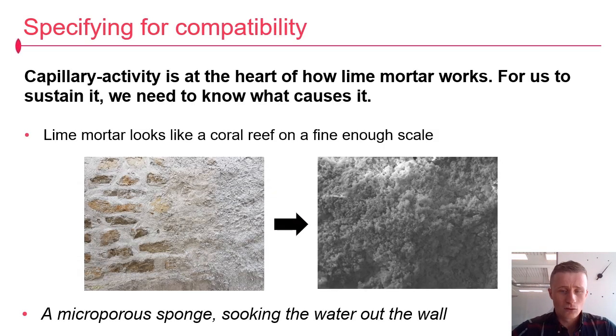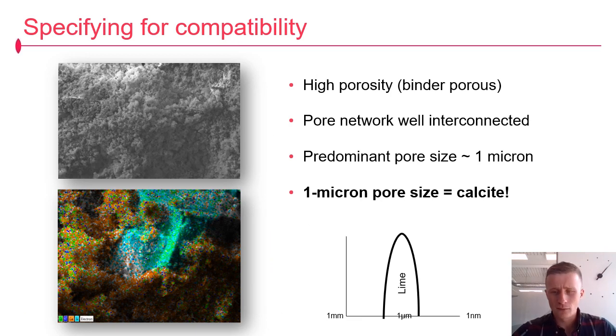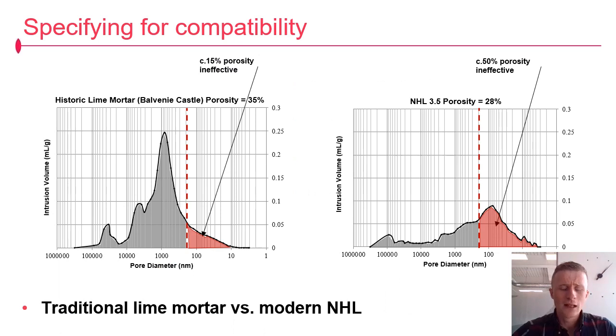So when you look at lime mortar on a fine enough scale, it is essentially a sponge, a coral reef looking thing through a powerful enough microscope. That's a sponge soaking up that water and drawing it out of the wall, and with the moving water come the soluble salts. What creates that sponge? Well, when you look at it through an EDX microscope and identify the minerals at work here, what you're looking at is calcite, that's carbonated free lime, in the mortar mix to create this optimal spongy microstructure. And we need to be replicating this mineralogy of our binder if we're going to create that sponge in our mortars today. So we need to do this by targeting an air lime or a feebly hydraulic lime to create that calcium carbonate, which creates that sponge.